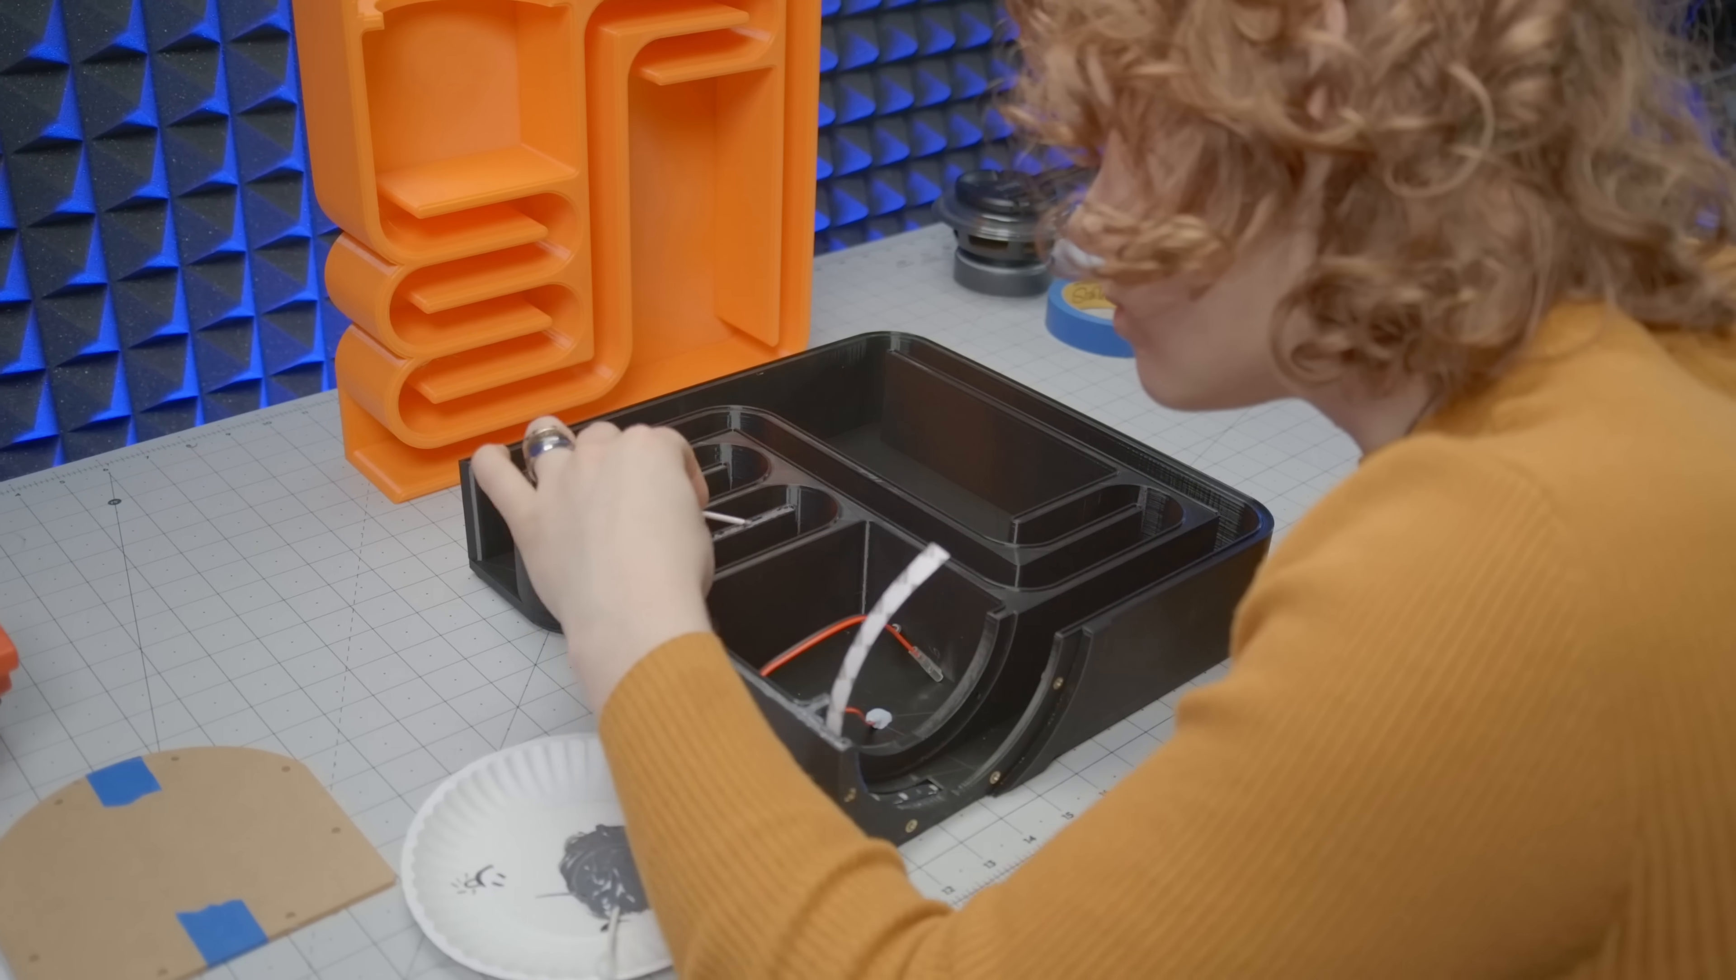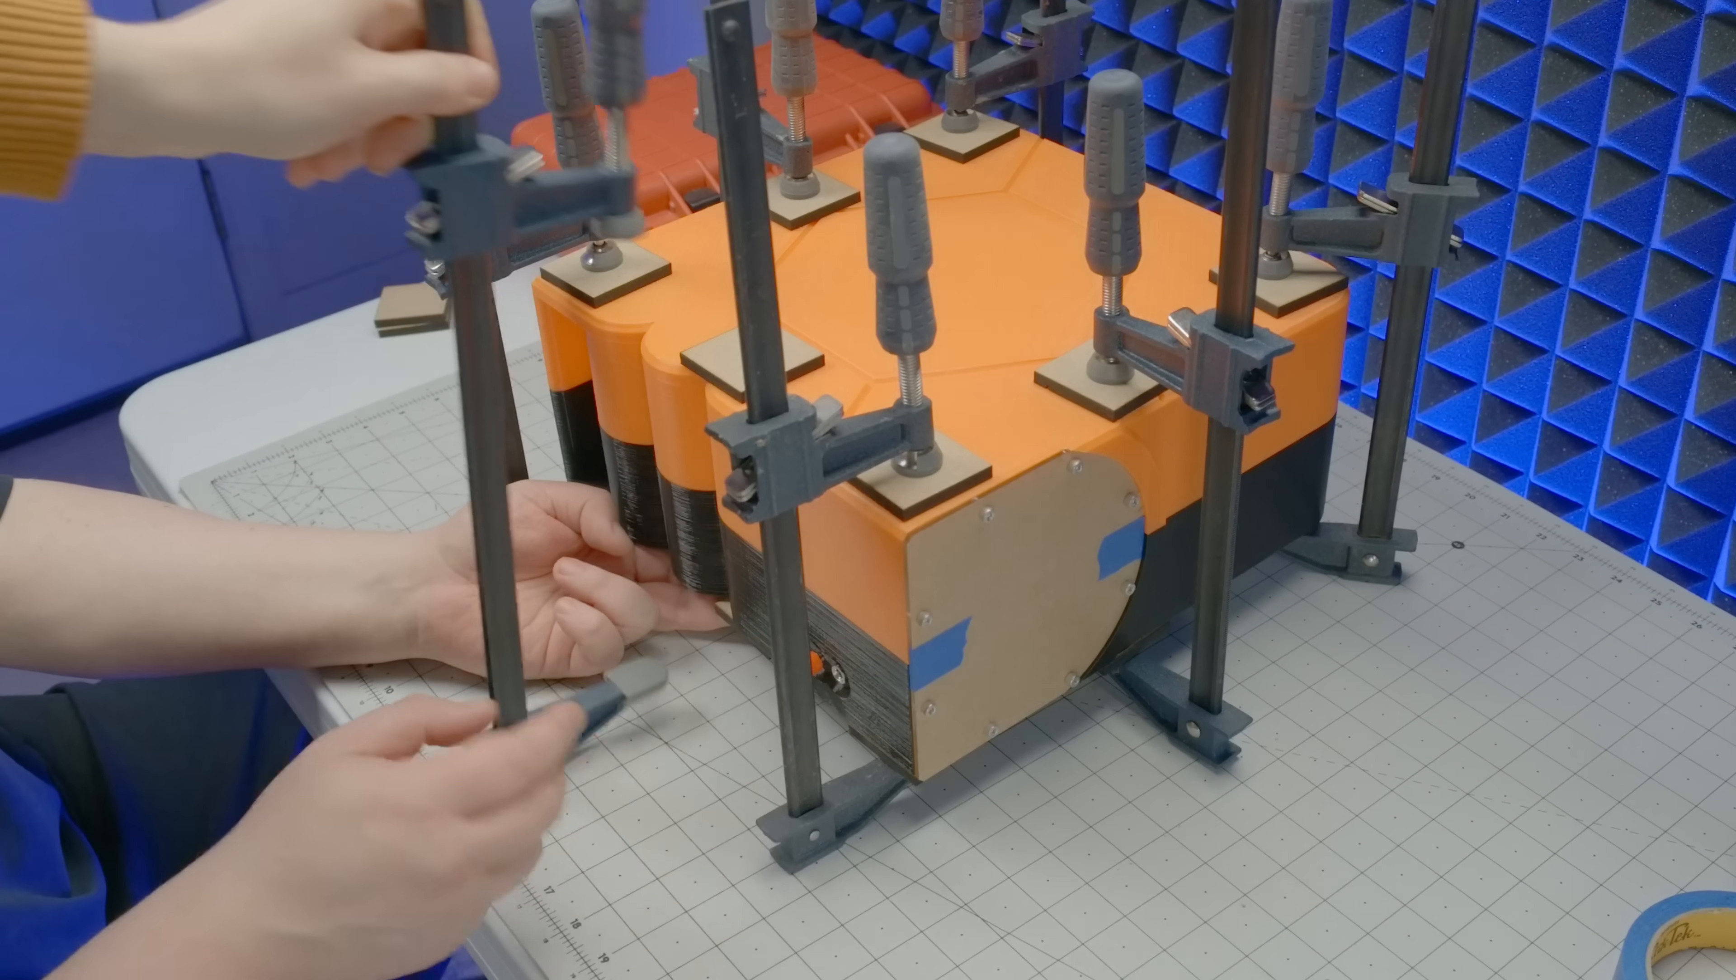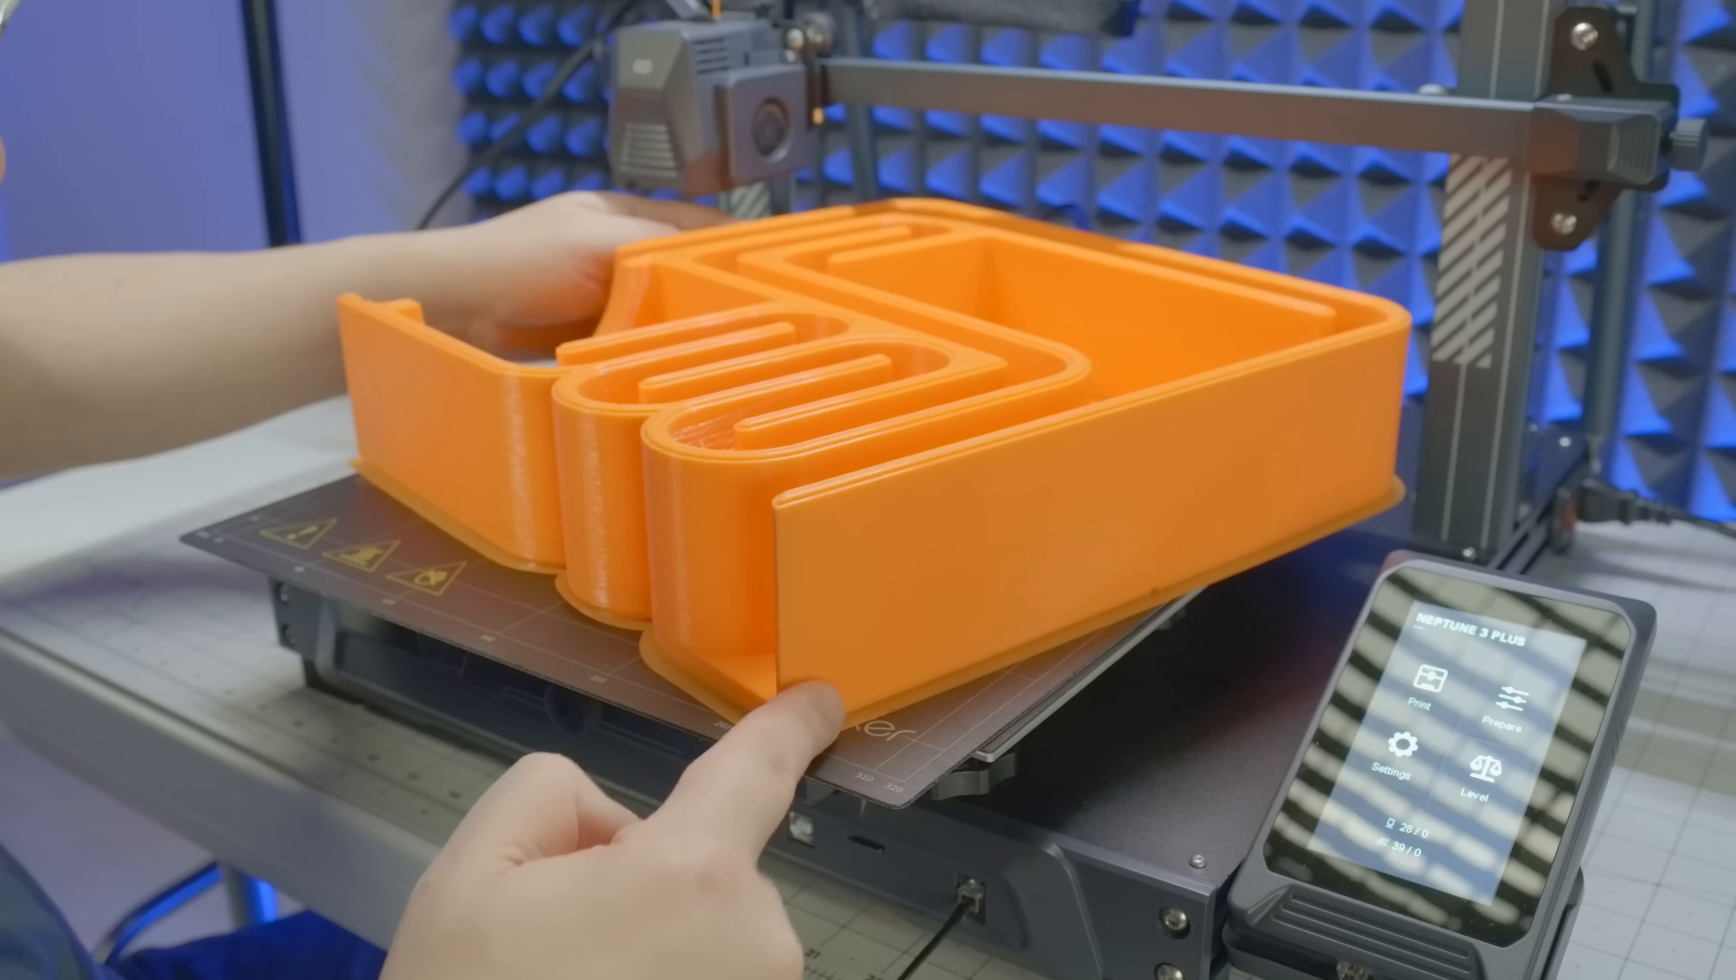So after I got done heat setting all these threaded inserts, I prepared to JB Weld the groove and here's where I discovered a potential drawback to printing this big. Right away, here I am attaching the access panel just to ensure that it stays aligned, but as I went to press the two halves together, it became apparent that the thermal contraction had caused them to bow outward, requiring a fair bit of clamping force just to get the outer walls to meet. And here I'd like to emphasize that this is not a problem with the 3D printer. In fact, this form of dimensional instability is due to a difference in the rate of contraction between the top and the bottom of the model as it cools, an inherent property of thermoplastic which unfortunately worsens as we print larger or use materials with higher melting points like ABS or PETG.